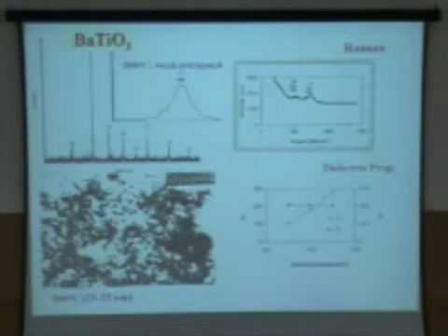Normally, ferroelectricity decreases as the particle size decreases. So you lose the ordered moment, and there are a lot of theories at what size it should disappear. So we showed that at 20 nanometers also we can see ferroelectricity. Of course, the dielectric constant goes down dramatically.